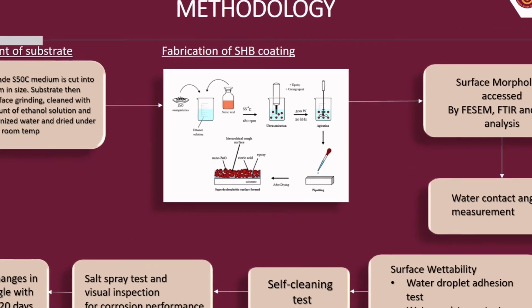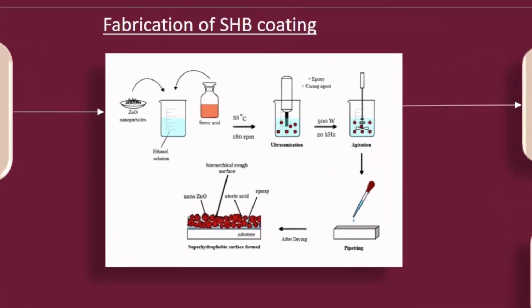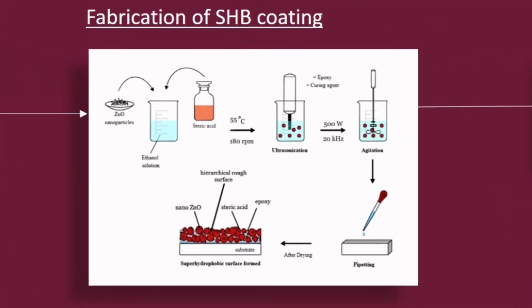Next, fabrication of the superhydrophobic coating. Zinc oxide nanoparticles and stearic acid were dispersed into absolute ethanol solution with constant agitation. Then, the mixture solution undergoes ultrasonication using an ultrasonicator probe. Afterward, epoxy resin and hardener were added into the suspension and mechanically stirred. The resulting coating was pipetted onto the substrate and dried at room temperature.